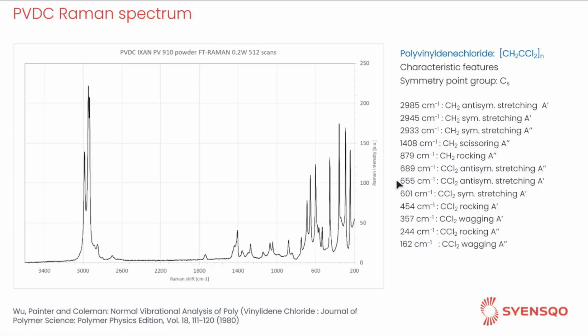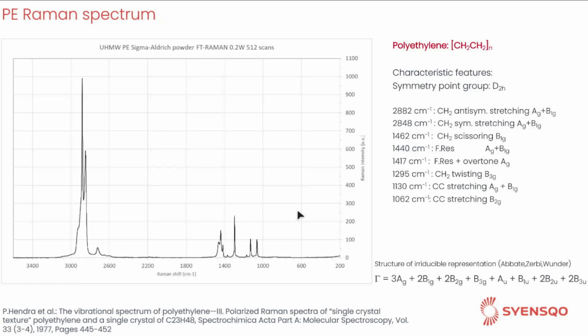Let's now have a look at the Raman side of the vibrational spectroscopy. Here, the survey FT Raman spectrum of the PVDC material. Again, we have observed characteristic features due to the presence of the chlorine atom in the backbone, especially related to the low frequency side of the spectrum, in which we observe carbon-chlorine stretching and deformation modes. This is the counterpart for the polyethylene.